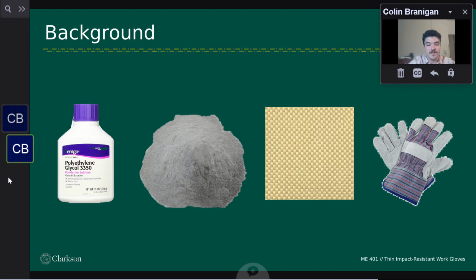The group initially had slightly different intentions for this project, and after conducting our first set of experiments, we were not satisfied with the results. We went back and redesigned our experimental process to provide more meaningful analysis and results. Additionally, we swapped our fabric from woven fiberglass to Kevlar due to the failure of the first material. Our testing method was inspired by the American Society for Testing of Materials, or ASTM. Specifically, the ASTM F1342 procedure for testing protective clothing material resistance to puncture was used. We also studied several academic articles that influenced our selection of materials. Our experiment differs from those already conducted by the ASTM because the STFs we used were different, as well as some of the testing methods that we employed.